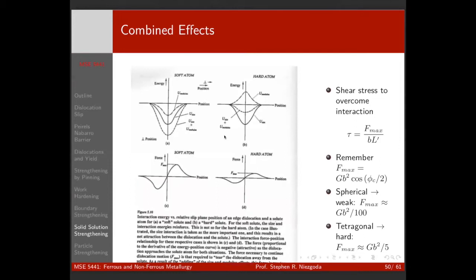So the idea of what you want is, if you have an optimal strengthening solid solution, you would want an atom with as big of a size difference as you can so that you don't get phase separation, right? And you want your solute atom, your alloying element, to have a lower elastic modulus than your primary element, right? Which is fine for steel and titanium. You can't quite get that for aluminum, right?